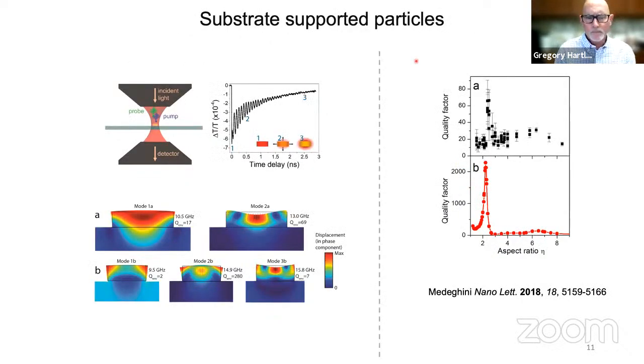What we'll be talking about for most of the talk now is the vibrational modes of these structures and how they depend on their environment. This is a slide taken from a fairly recent paper, again from the Lyon group, Fabrice Vallée and Natalia Del Fatti, on some lithographically made structures, so structures that are stuck pretty hard onto the surface. You see oscillations here, that's the breathing modes. In these experiments, they changed the aspect ratio, the width compared to the diameter of these little structures that they made.